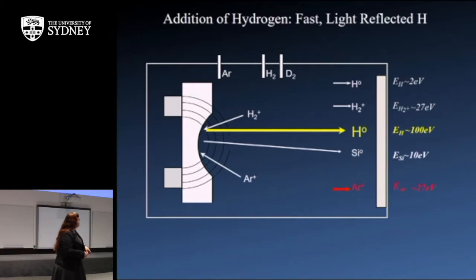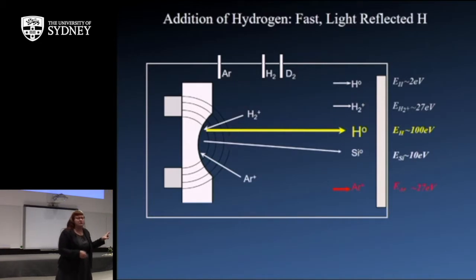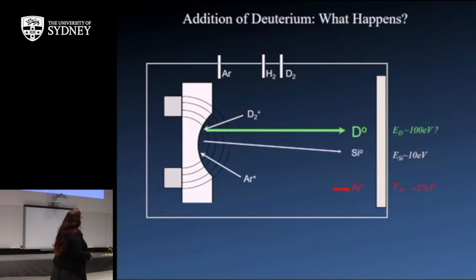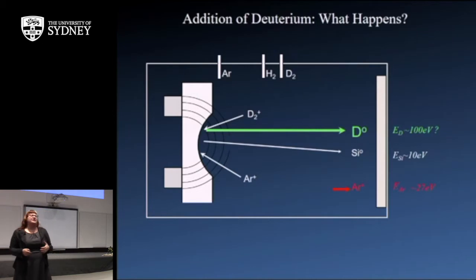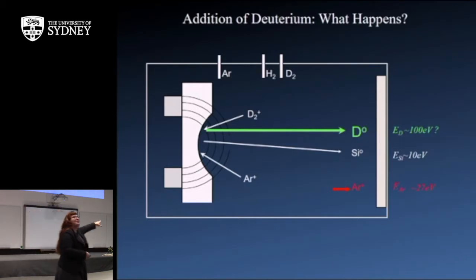So what do you actually see? There's a bunch of this neutral hydrogen that actually reflects off the target that actually goes and can impinge pretty deep into the film of this material. So when you change it to deuterium, we measured this, the flux of the energy doesn't really change. But you have a lot more momentum transfer because the deuterium is much heavier. If you have more momentum transfer, you're going to restructure the film more.